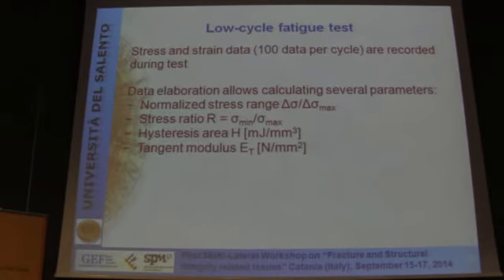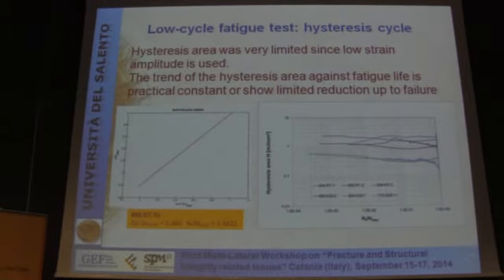During the test, we recorded stress and strain data, load and deformation exactly. We collected about 100 data points per cycle, so we are able to calculate, for all cycles, the stress range, the stress ratio, the hysteresis area, and the tangent modulus. And this is an example of what we obtain.